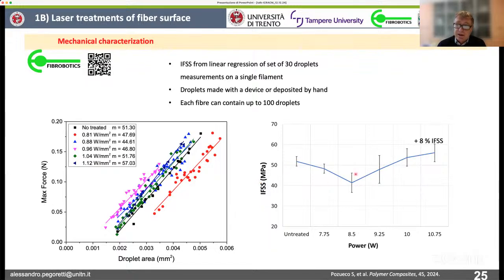And as far as we are concerned, the laser effect, the effect of the laser treatment, we can see that initially, when the power increases, we get a decrease of the interfacial shear strength. Probably here we are just removing the coating on the fiber, the sizing. And after we can have some positive effect, but with a limited extension. So at the most we reach 8%, but with a large standard deviation.